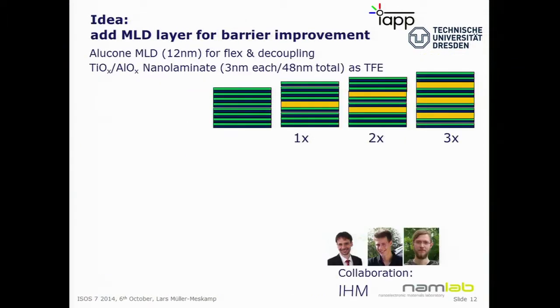So we put the laminate, in this case now 3 nanometers each layer, on top of our calcium test or device. And then we wanted to introduce alucone layers, MLD layers, in between for flexibility and decoupling of defects. So we have a different setup. So now we have here 48 nanometers of this nanolaminate.